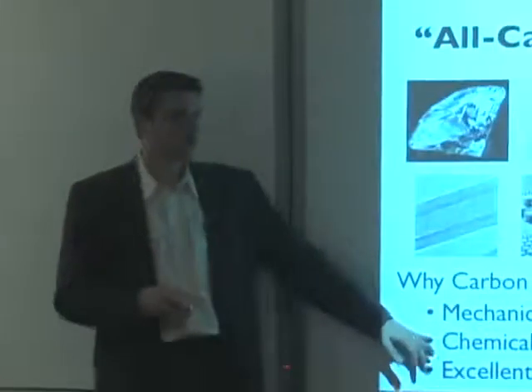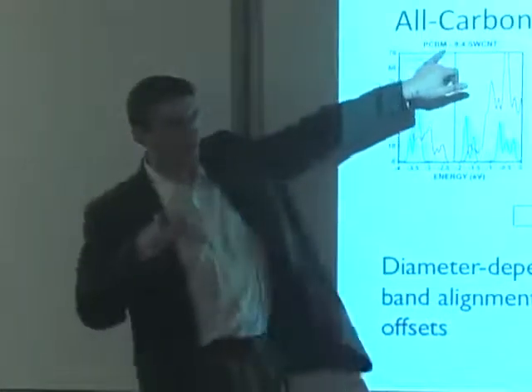So one of the things that we started doing is we said, could we make bulk heterojunction cells? Could we put fullerenes and just blend them with nanotubes? The first question you'd have to answer is how these things line up. PCBM is just a functionalized fullerene, a fullerene with a little tail. We can put that in the computer up against different size nanotubes, look at their density of states, and decide whether it's a type 1 or type 2 junction that forms. The ones circled in purple, those diameter tubes, form a type 2 junction. The ones circled in black form a type 1 junction, which would not be favorable. So we can already look at these materials and comb through phase space to see where you might have good materials to blend.